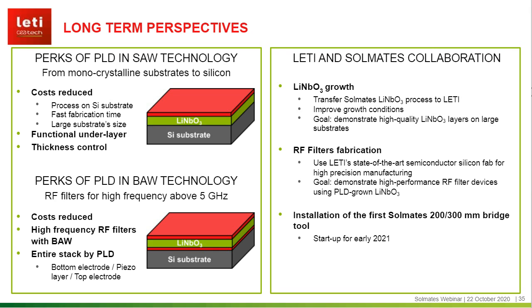As for the Leti and Solmates collaboration, on one hand, the deposition process of lithium niobate thin film will be transferred, and we will try to optimize it to be able to demonstrate the process on various and large substrates. And on the other hand, Leti will use its competencies in silicon fabrication to demonstrate the high frequencies that can be reached with radio frequency filters in lithium niobate thin film grown by PLD. All this will be with the installation of the first 200 millimeter bridge tool of Solmates that will operate at the beginning of 2021 at Leti.